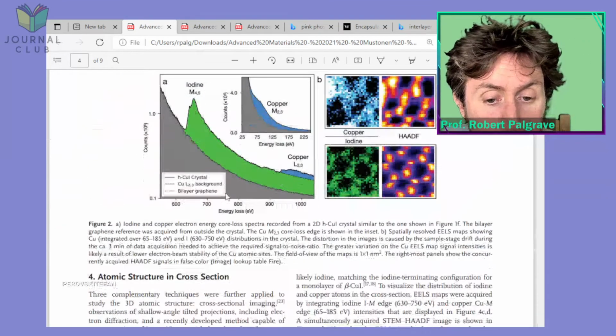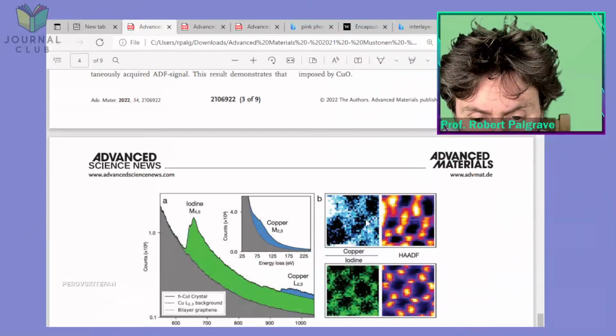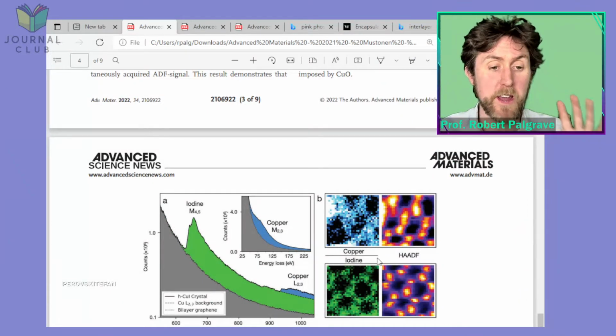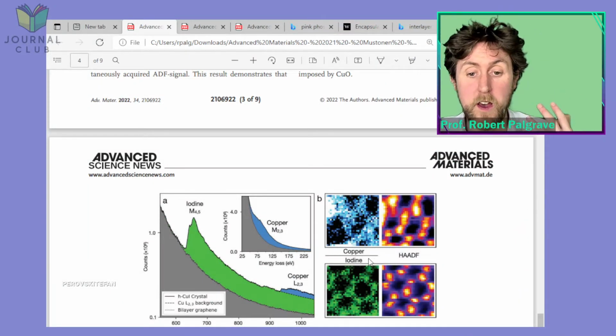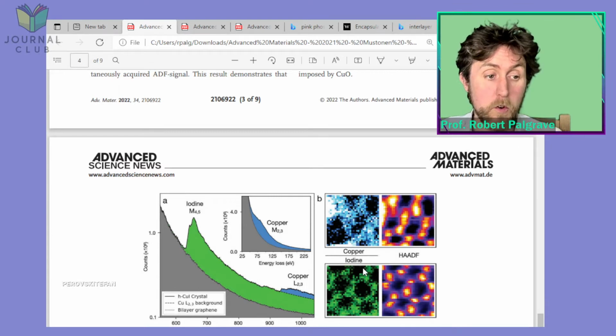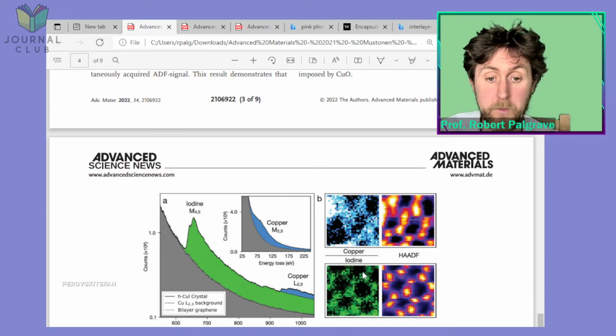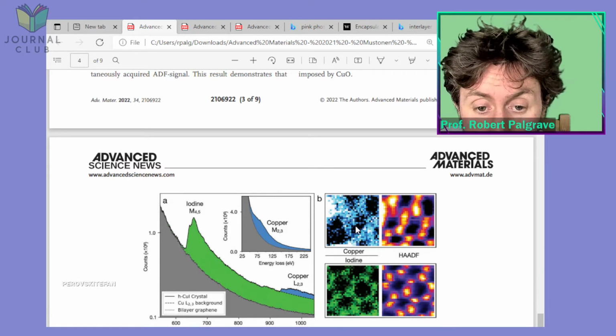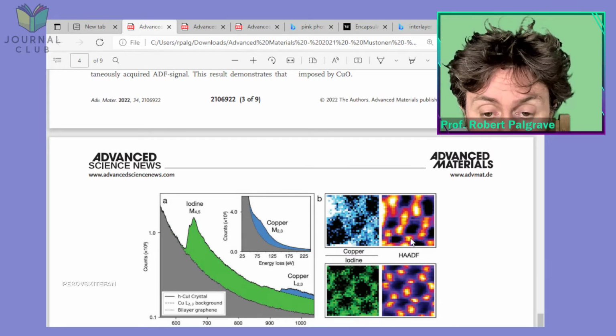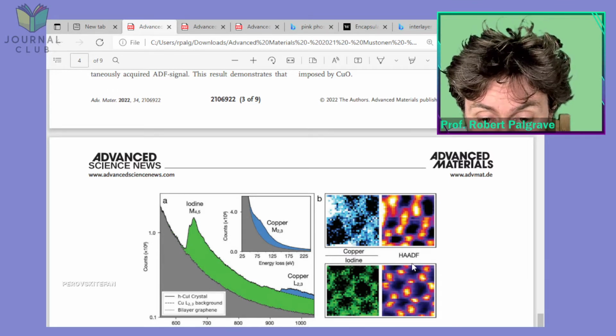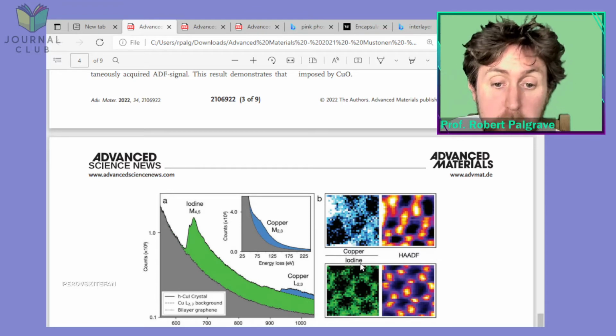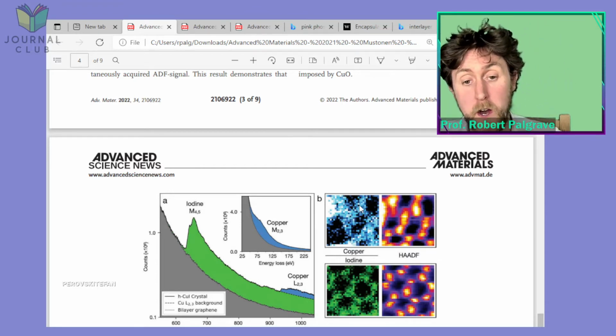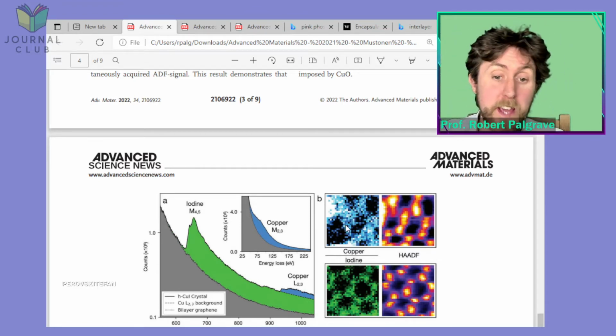Yeah, so they show some EELS images here. EELS is a nice technique because you can do it at the same time, in the same equipment as the TEM, the transmission electron microscopy. So you can compare the HAADF image here, which is what we were just looking at before, and superimpose the EELS image on top of that to give you the chemical composition.